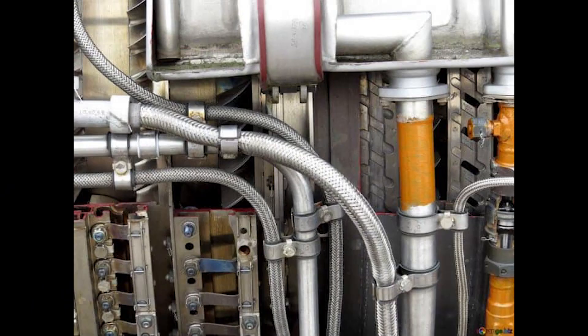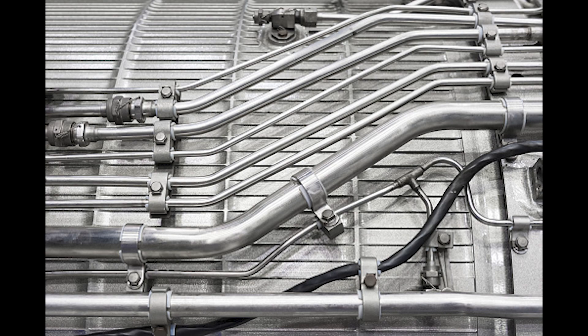An official investigation was carried out, which showed fatigue failures of the pipes in both hydraulic systems had led to a partial failure of the flying controls. The F-14 Tomcat consisted of two hydraulic systems which were widely separated. These lines were connected using screws, threaded valves, and components which are bulky and prone to leakage.